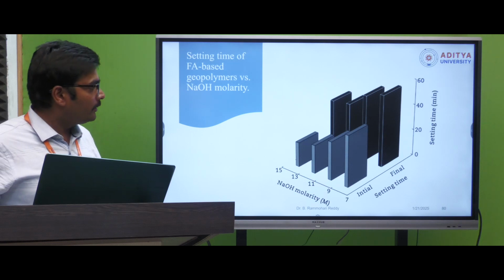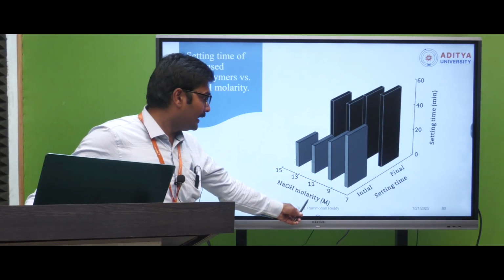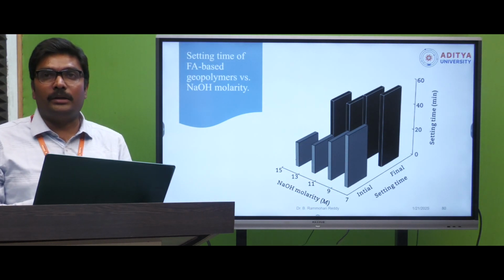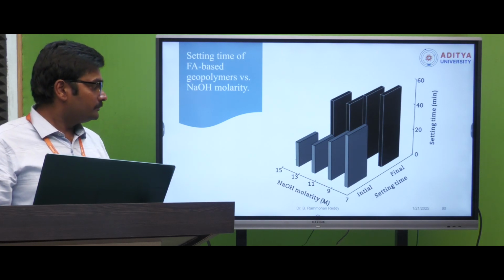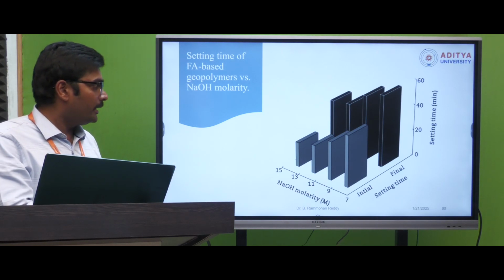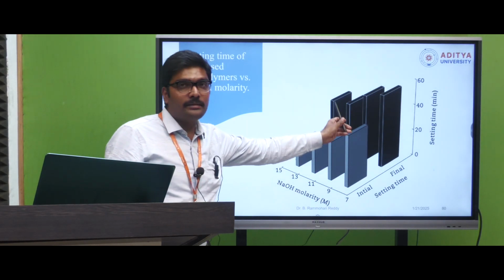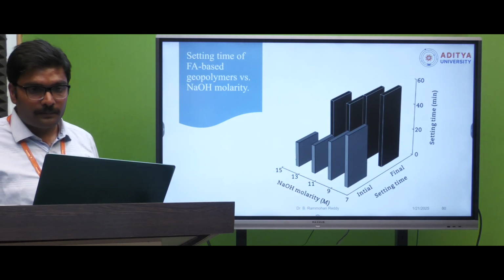Similarly, the molarity versus the initial and final setting time. With lower molarity of the NaOH solution, the initial setting time and final setting time are high. If molarity is increased from 7 to 15, you can see the initial setting time is reduced and the final setting time of the concrete is also reduced.